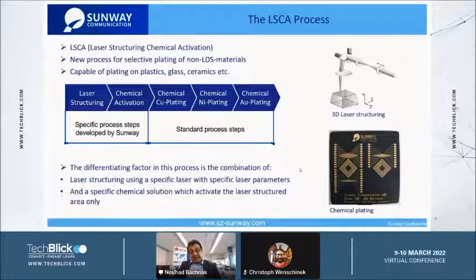So the LDS process is the most used process now. We have about 80 to 90% of the projects in 3D MID we do with this process. But here you need this additive inside. Let's say if you need a transparent material and you add this additive, this will be not transparent anymore. Or if you have a biocompatible material and you add this additive in order to be able to structure and plate it, this will be not biocompatible anymore.